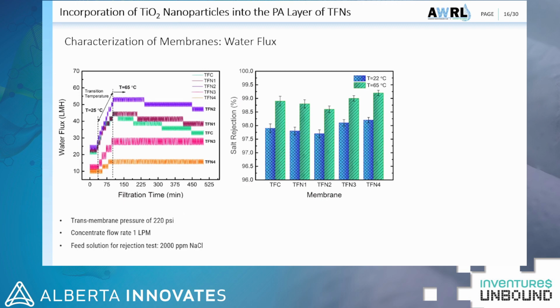Water flux tests showed that by adding more TiO2 nanoparticles, the flux decreased as compared to the pristine TFC membrane, but remained stable, which is one of the characteristics of thermally stable membranes. For the pristine TFC membrane, we observed continuous flux decline over time. But in the TFN membrane, when we increase the concentration of the nanoparticles in solution, you can see that the flux is less, but at least it is consistent and stable. The rejection results also showed that the TFN membrane with the highest loading of TiO2, like TFN4 that you can see here, even has a higher salt rejection than the TFC membrane. This shows that non-selective voids are not created, and we achieved good compatibility of the nanoparticles with the polyamide matrix in the TFC RO membranes.